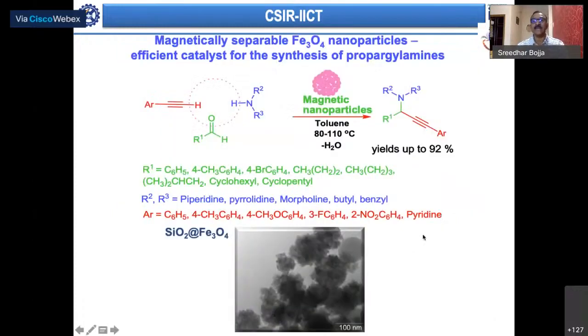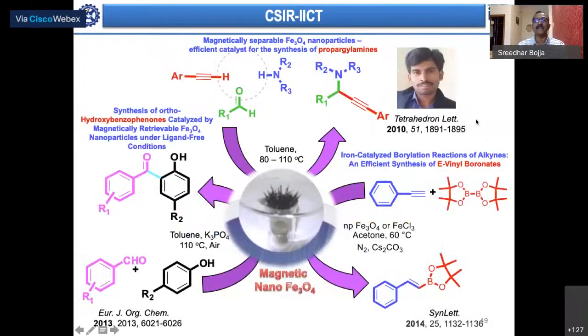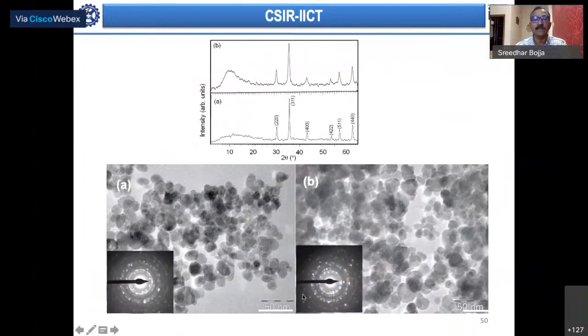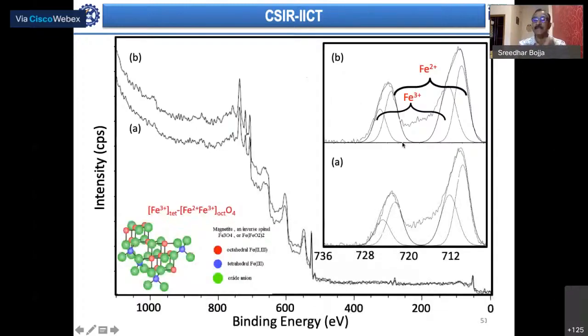And this was the first reaction we worked on, the three-component coupling for the synthesis of propargylamines. And then starting that, we did all sorts of things and tried to work on this kind of iron oxide nanoparticles. But we wanted to do something different here also. These are the TEM images. They were about 25 nanometers in size before and after catalytic reactions. And these are the XRD images that you can see are okay. Then here comes that XPS spectrum again.